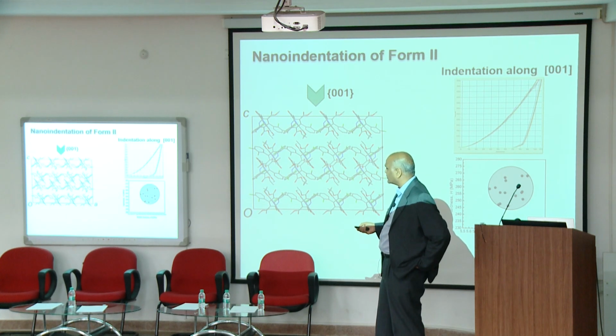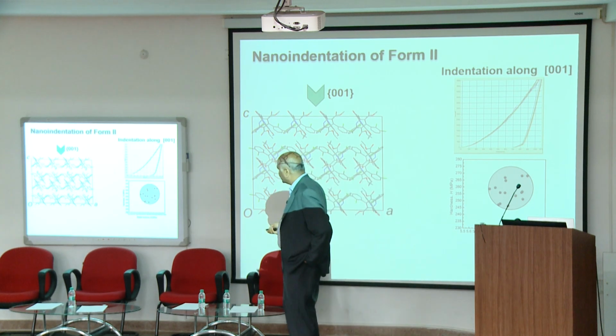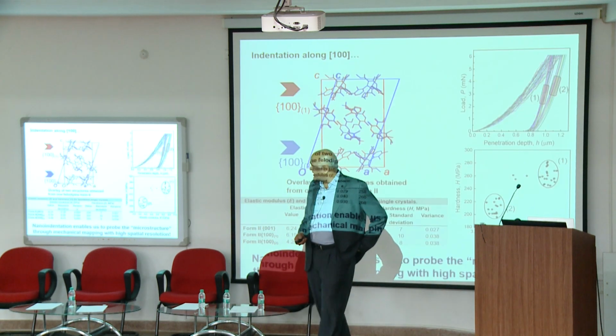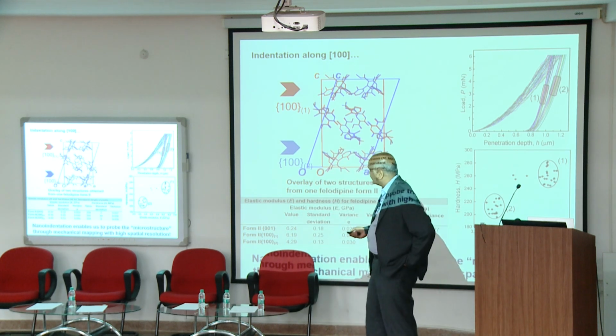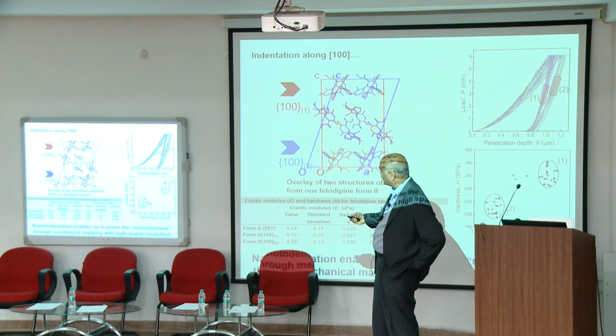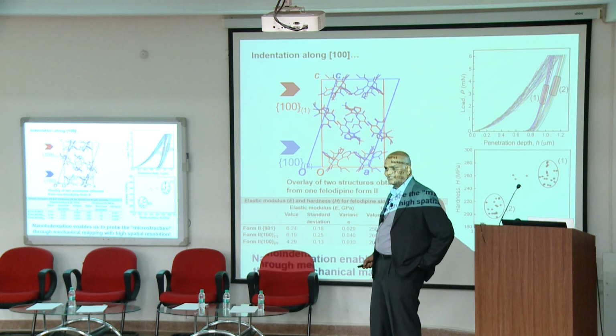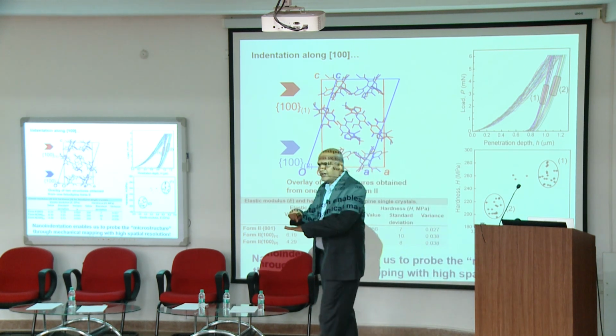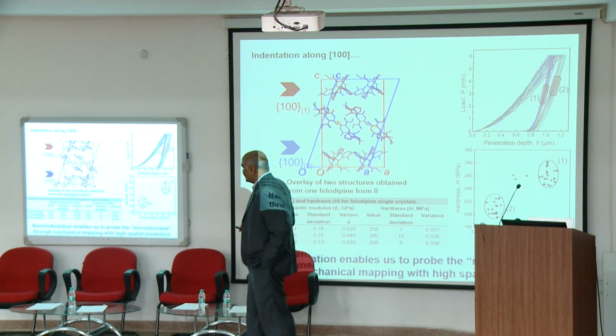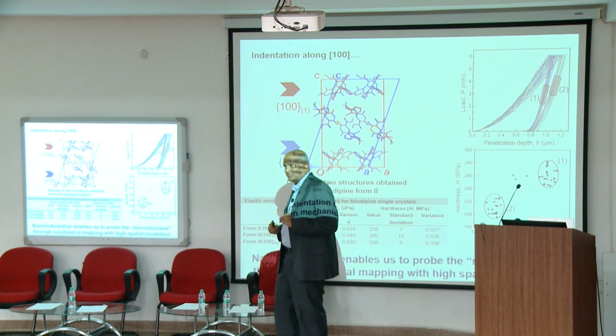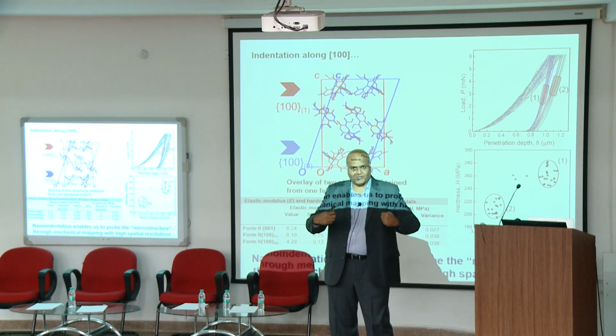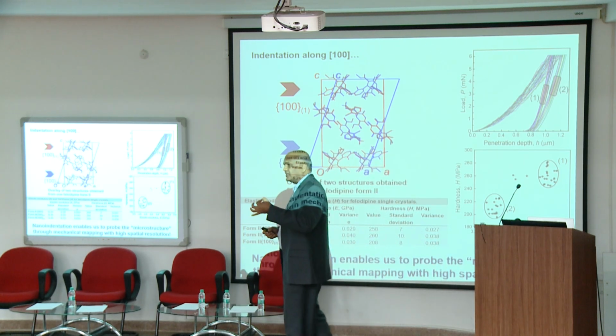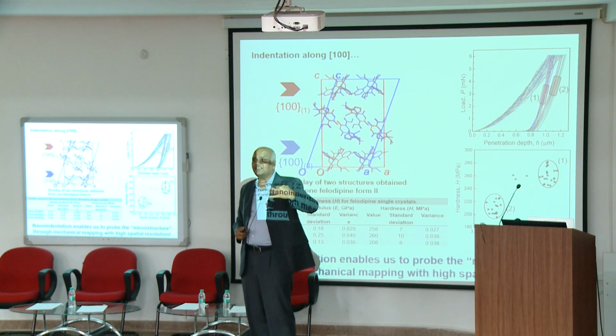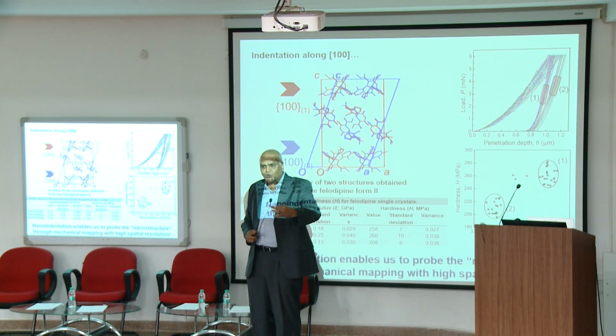So when I indent from the top, there is some stochasticity, but that is because we are measuring local properties, but all the curves are the same. But when I indent from the side, these are the responses. You can see they are already segregated into 2, right? So I get very distinct responses, and there are some in between because we maybe have the interface of those. But this tells me that Xray diffraction would be very, very difficult to resolve, right? With the indenter, because this is a nano indenter, I can do it with very fine spatial resolution. I can actually go and look at it.